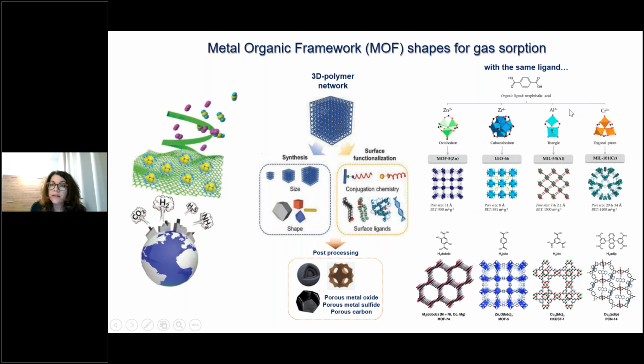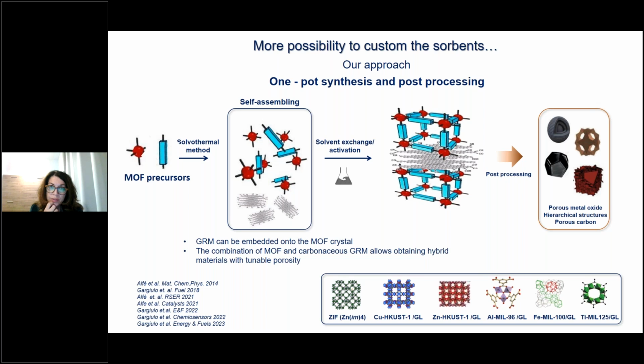Just to give an idea of the flexibility of the shape and internal performance, just having the same ligand and changing the metal inside the metal organic framework, you can obtain different porous structure and different shape, specifically thought for CO₂ applications. Another approach we are currently using in our group is to embed inside the metal organic framework, inside the structure, active molecules such as graphene or graphene functionalized with other molecules. As you can see, the possibilities are very, very huge. And also, after post-processing, you can obtain a wide array of functional materials.